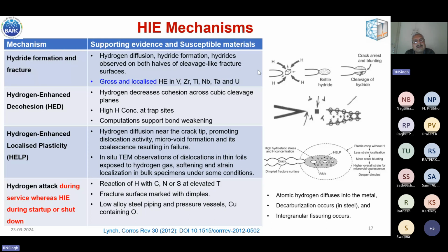So how it will interact, how it will affect the cleavage energy, that is the question. In most embrittlement mechanisms, at higher temperature the metal becomes more ductile, more tolerant. So that's why this embrittlement effect is not observed at higher temperature. In our case also, in the hydride form, you must have seen that just at 250, 300 degrees Celsius, we are in the upper shelf, and there the fracture toughness is as good as the as-received material, even with a radial hydride orientation.